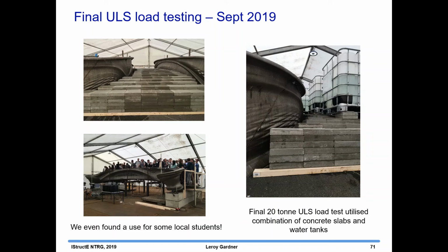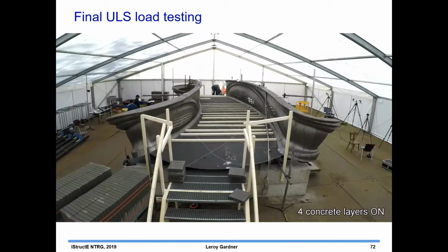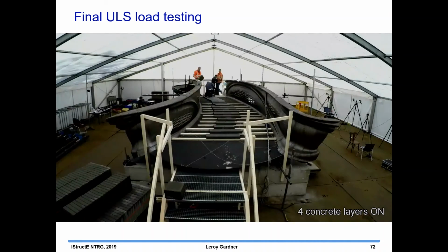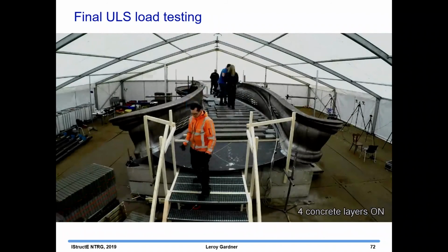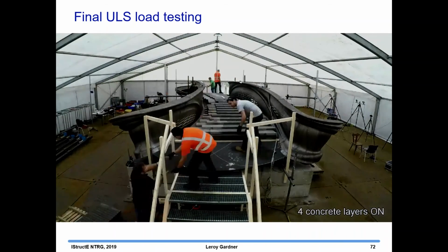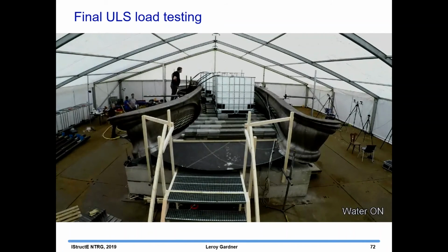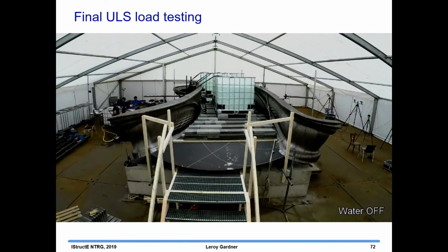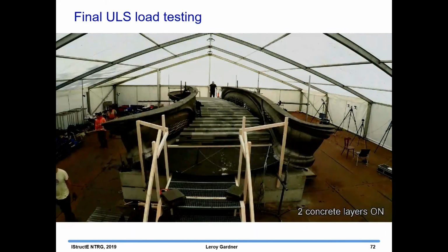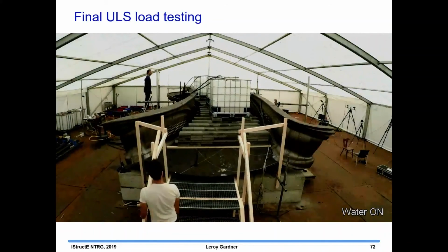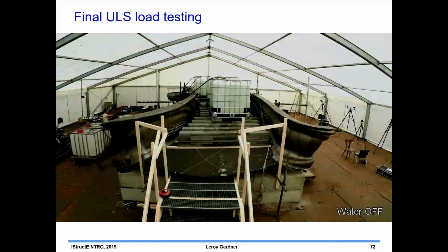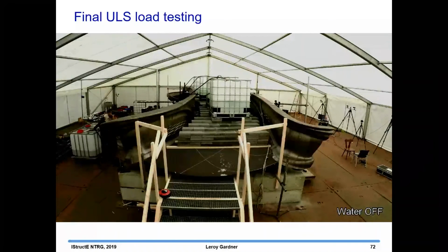So I've got a time-lapse video which shows how this process worked. That's us putting the layers on the bridge in a sort of organised fashion, layer by layer, trying to keep it evenly distributed. Then the water tanks were put on and filled up. That took us up to about 15 tons. And then we went back down again with the water. 2 further layers of bricks, water tanks back on, and then up to the ultimate limit state design load, which was close to 20 tons.